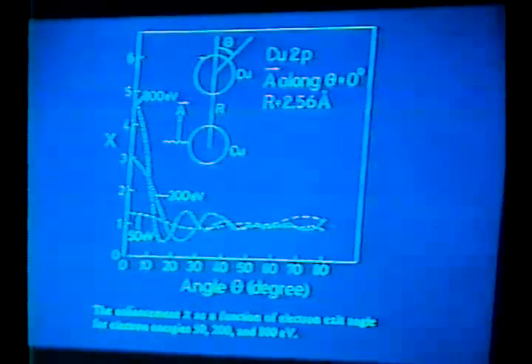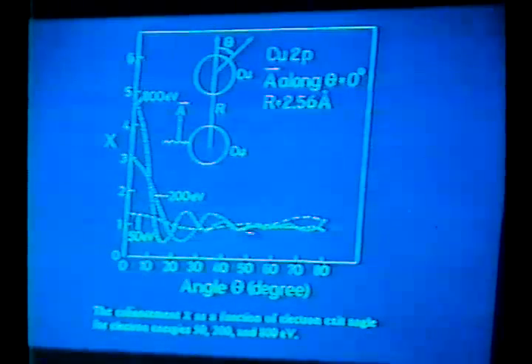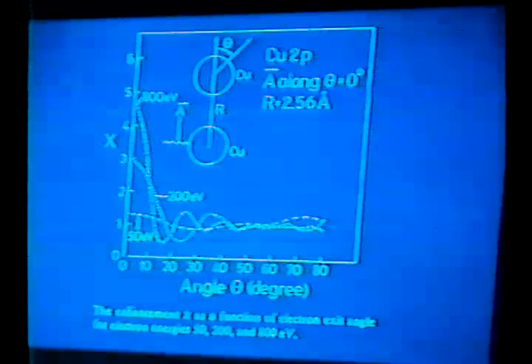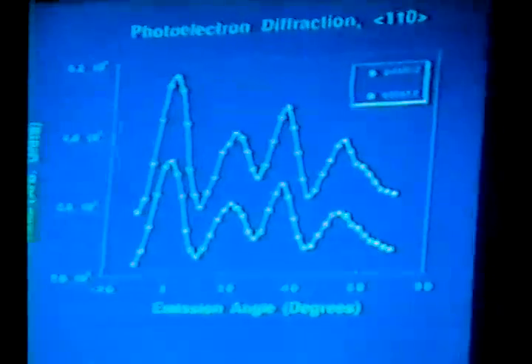There are two mechanisms. Both of them are, of course, part of the diffraction. One, where the photoelectron that initially propagates as a spherical wave is refocused on the scattering atom. That's called forward focusing. And then there are scattering directions which give rise to the diffraction order. Forward focusing is wavelength independent, the scattering is wavelength dependent, and for high enough energy of photoelectrons, the forward focusing dominates over the diffraction phenomenon for the first and higher order. We have used this first for verifying the structure of the palladium surface, and of course you can also determine the relaxations of the various metal planes and so on.